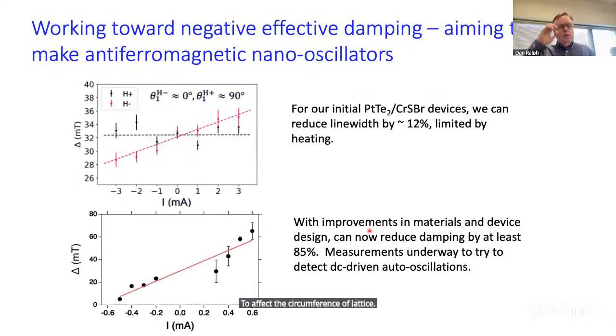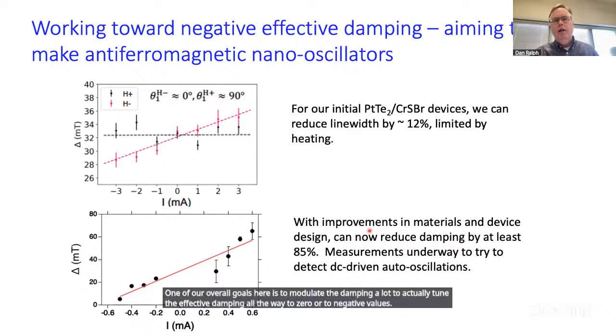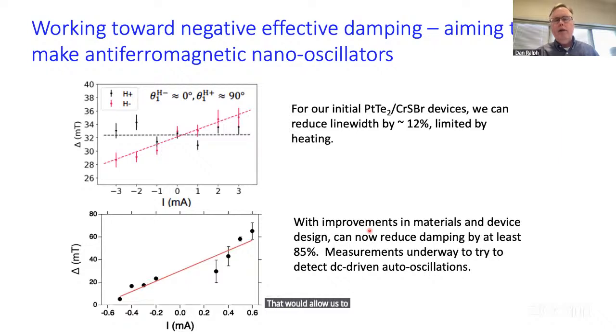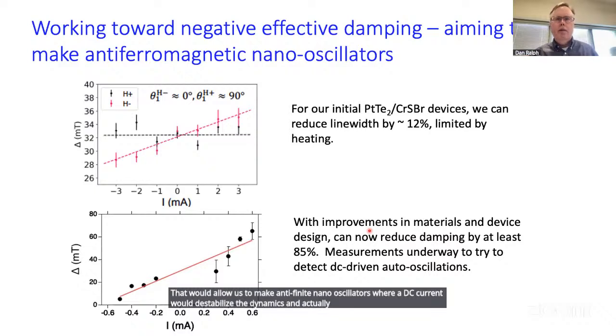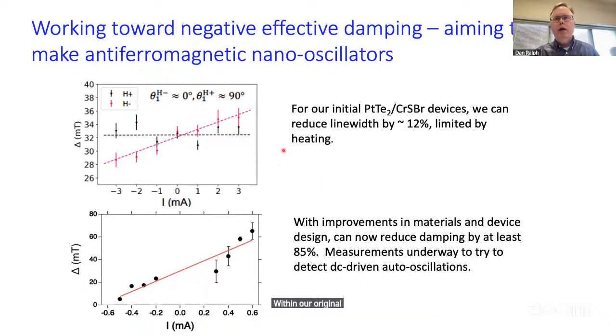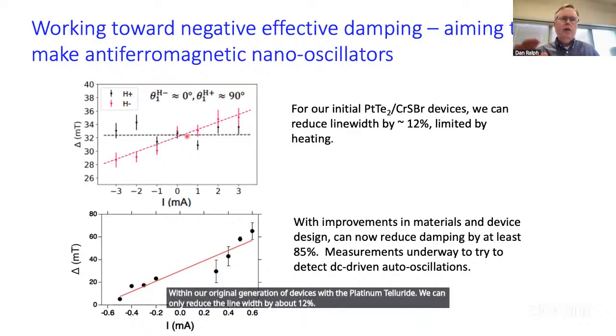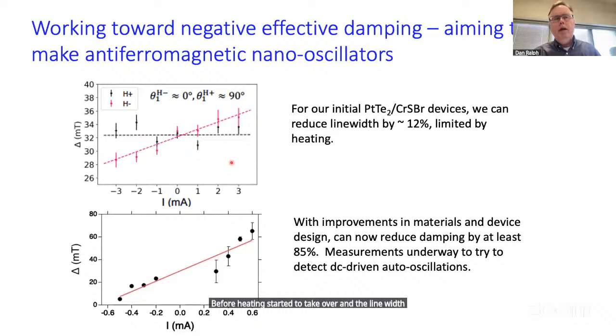Okay. So one last comment just about how much we can actually modulate things. One of our overall goals here is to modulate the damping a lot, to actually tune the effective damping all the way to 0 or to negative values. That would allow us to make antiferromagnetic nano-oscillators where a DC current would destabilize the dynamics and actually allow the antiferromagnet to start self-oscillating. Within our original generation of devices with the platinum telluride, we can only reduce the line width by about 12% before heating started to take over and the line width would start to go back up as we went up to higher magnitudes of negative current here.